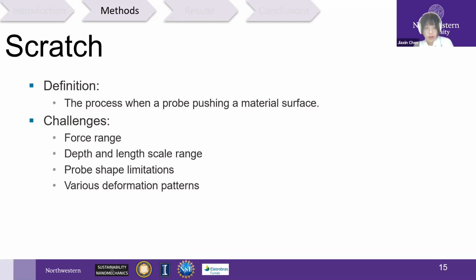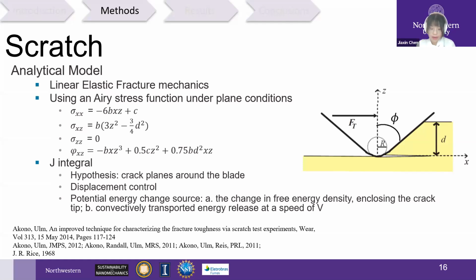Scratch itself, in other words, is the process when a probe pushes on a material surface. There are challenges during scratch: the force range, the penetration depth, the length scale range, and the probe shape limitations, in addition to various deformation patterns. In terms of the analytical model of scratch testing, we assume linear elastic fracture mechanics and an Airy stress function for sigma xx, sigma xz, and also phi xz, and the plane conditions were derived accordingly.